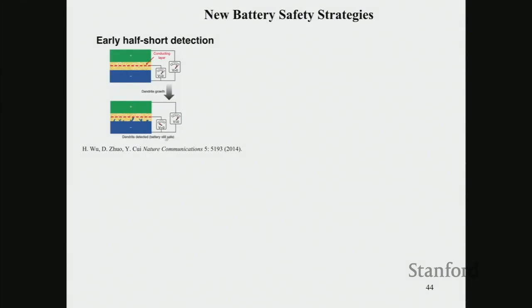One idea is, if you have internal plating of metallic lithium, can you, inside this battery, with the separator, the positive electrode cathode and anode separated, the yellow color. In the middle, this red dashed line is a metallic coating, about 100 nanometers or 200 nanometers, very thin, put in the middle. And instead of having two electrodes, let's have three electrodes for each battery cell. If you have shorting happening halfway, you detect this middle layer against your anode. You see the voltage goes to nearly 0. That tells you the shorting is coming. It's halfway. You had better stop charging your battery and not use it anymore. So make it safe. That's our solution number 1.